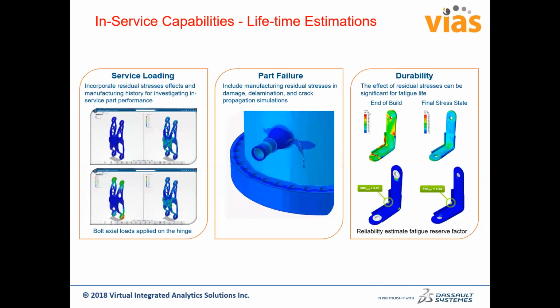Depending on how your loads are, a crack tends to propagate in the maximum tensile loading direction. So if you have complex loading and complex geometry, which most of your additive manufactured parts will have, then it is not very easy to predict the crack growth. This simulation capability will accurately predict that crack growth. Looking at the crack growth, one can come up with the remaining life, or how many cycles of thermal or pressure loading I can subject this component to. What will be my maximum load? Will my crack be stable under the maximum load? All this information can be obtained.